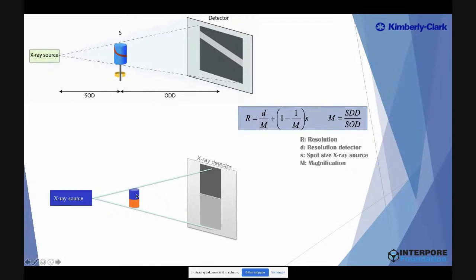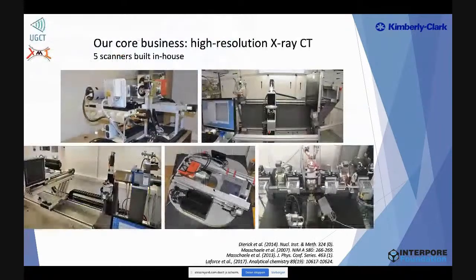This way you get a higher magnification, and this allows you to also have a better resolution. And that is why when you look at CT research, often the samples are rather small, because what we want to do is image them at the highest resolution possible. And so we try to find an optimal sample size compared to the obtained resolution.